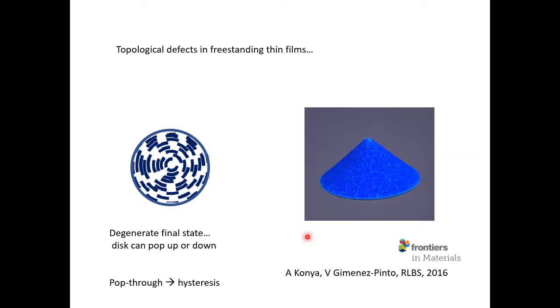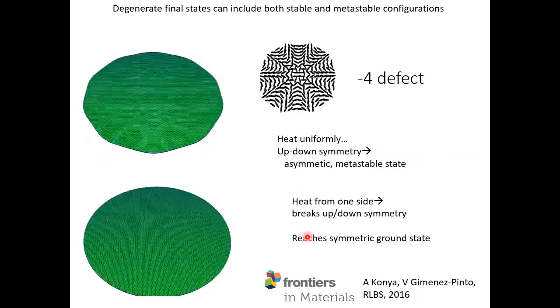So this is what we can learn from the finite element simulation that we couldn't learn, for instance, by just doing analytical calculations where we often neglect the bending energy of the thin film. If you treat it as infinitely thin, you will miss the pop through hysteresis.